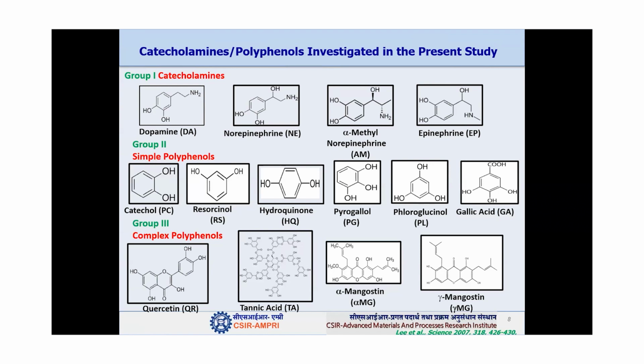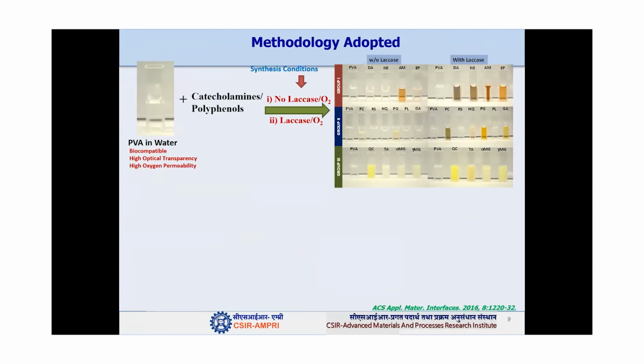So three categories of compounds we have used, and then this is just the methodology I'm showing, how we have actually prepared those films. So we have taken the PVA, this is polyvinyl alcohol, it's a polymer. Then we have included these catecholamines and polyphenols in that particular PVA, and then we made the solutions. Since these compounds can be polymerized, we have used laccase, which is an enzyme, for the polymerization of polyphenols. And then this is without laccase solutions, and this is with laccase solutions.